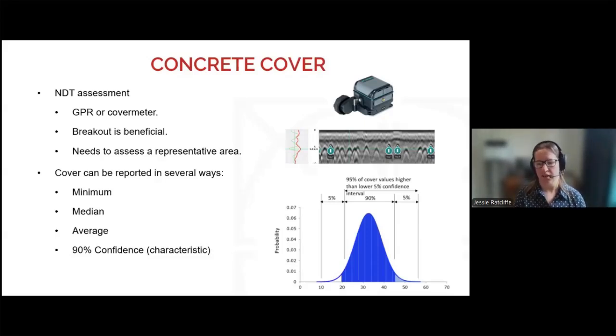So we can consider minimum cover if it's a critical element, or we want a particularly conservative assessment. But that might be overly conservative if you just have the one bar that's sitting a bit high and can be treated locally. Median and average are more common, but you could misrepresent the risk in the structure if the cover is very variable. And so often we use the 95% confidence interval cover found via statistical analysis, and that covers most conditions in the data set.